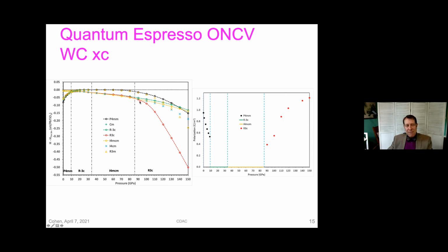But then we found, and this is what's really been soaking up all of my time, that at really high pressures, above 90 GPa, this ferroelectric R3c phase comes back in with a vengeance. So there really is a very, very robust prediction of ferroelectricity at ultra high pressure, even though it's non-ferroelectric for this whole range in here. And we were worried that this was some kind of numerical artifact for a long time, and have been working real hard to prove that that's not so.